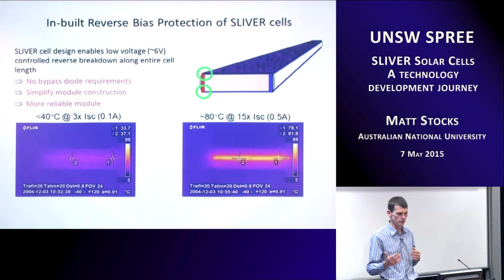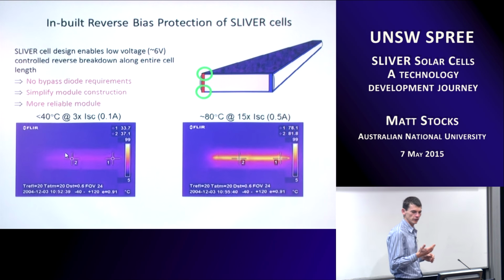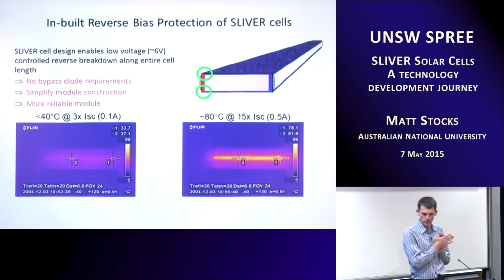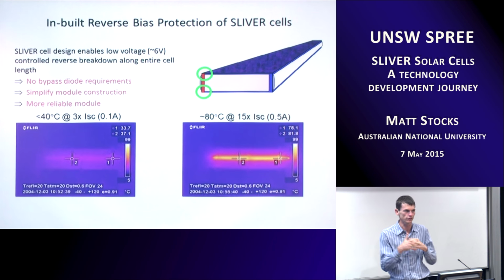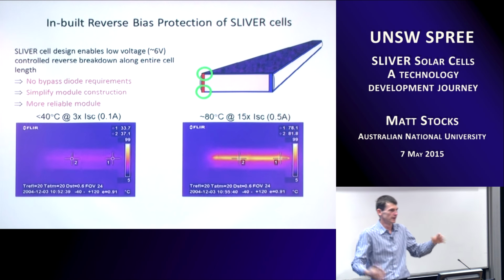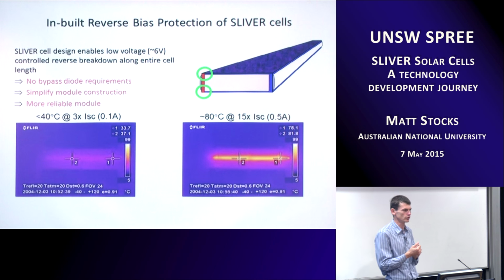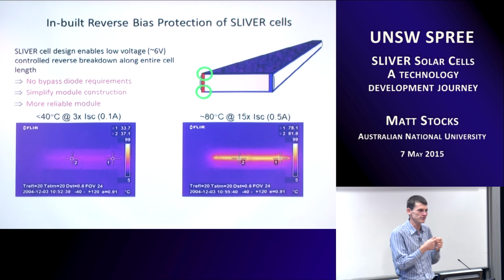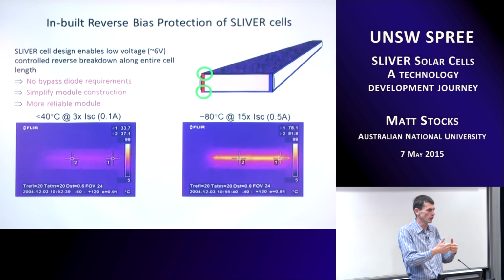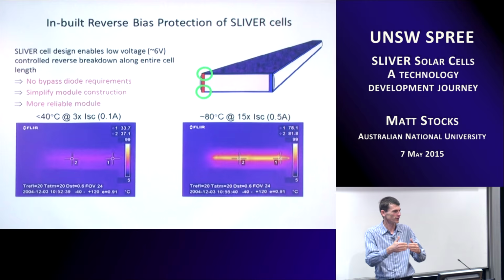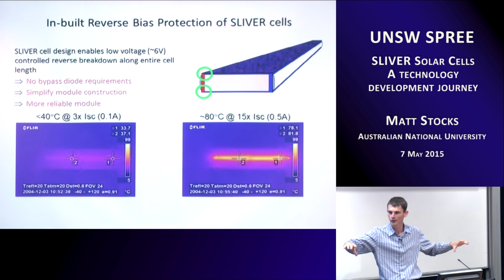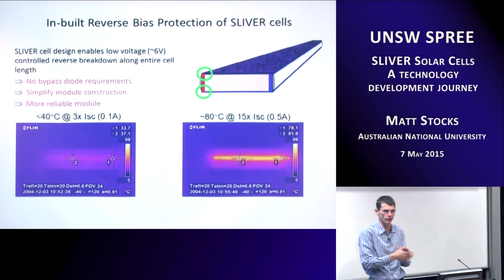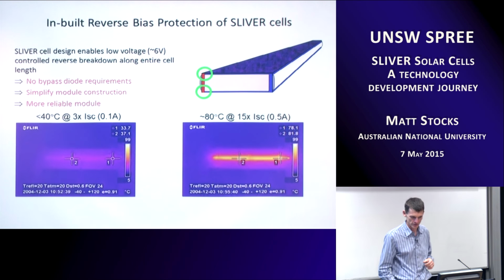And what you can see here is as you push the cell into reverse bias, in this bottom left case, we're pushing 3 times ISC and the cell's barely warmed up, to everything less than 40 degrees. Even if we pumped 15 times the short circuit current of an individual cell, imagining lots and lots of current being fed into one bank because of some sort of defect or other issue, temperatures were pretty controllable. You can see the cell glow up as you increase the current. It would turn on at one point at something like 5.8 volts, then gradually at 5.9 volts the next section would glow, and then at 6 volts. You could control this along the cell and so spread the load of any heat being dissipated within the cells.